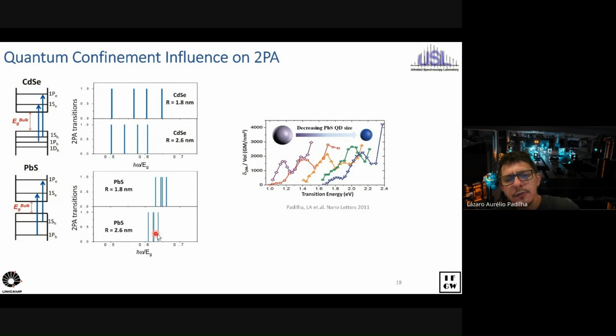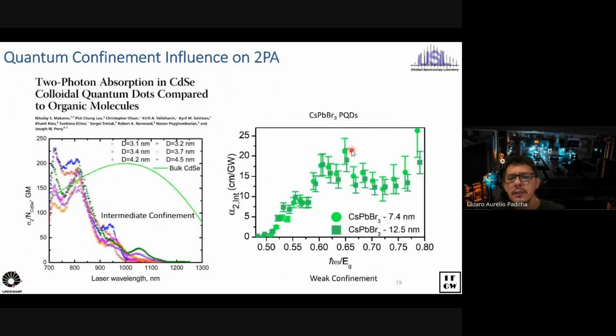And this unique structure makes all the transitions kind of move together when you make it smaller, in a way that it's not spread as it is here. They actually kind of group together. And what we see when you study lead sulfide is that, in fact, as you make it smaller, the volume normalized two-photon absorption kind of increases.